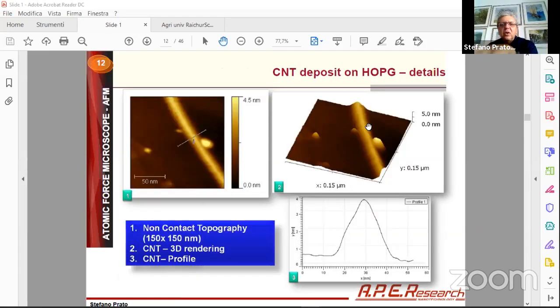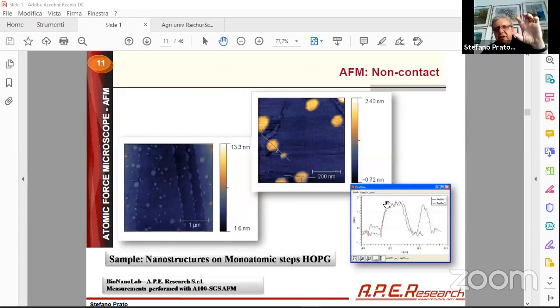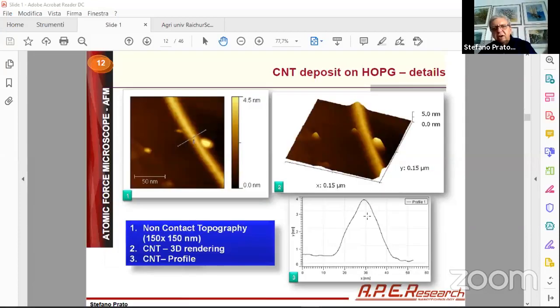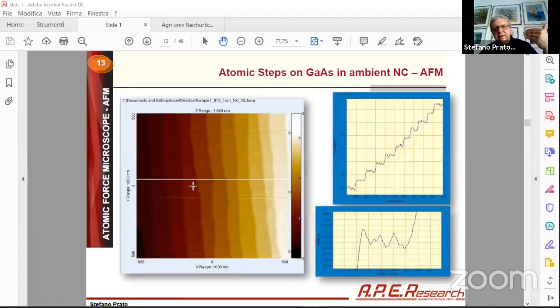Resolution. So, as I said, this is 1.5 nanometers tall. This is 3 nanometers tall. That is very small. But what is the limit that you can achieve? If we zoom, now we move to a solid state sample. This is a gallium arsenide where you have some atomic steps. Here you see a series of crystal steps. You have around 10 terraces here, and from one terrace to another, you can see in the profile here, you have an atomic layer.